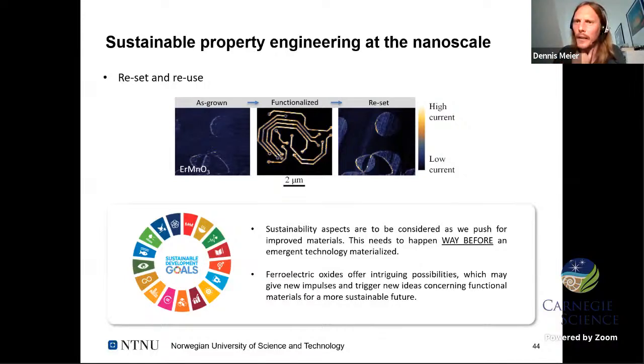Sorry, can you repeat that again? Yeah. So he asks if the point defects are like doping in a semiconductor, or are they actually changing the polarization structure? So with the resolution we have in the images, we don't see any displacement of the atoms beyond what we see anyhow for the polarization. So within the resolution, no change. So they're really hidden, not visible defects.